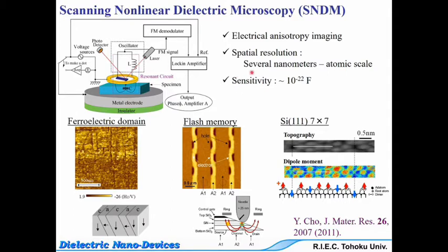And as this microscopy technique has quite high sensitivity, of the order of 10 to the minus 22 farads, using this technique we also have succeeded in visualizing stored charge in semiconductor devices. Moreover, under ultra-high vacuum conditions, we can measure the dipole moment with atomic resolution by using the SNDM.